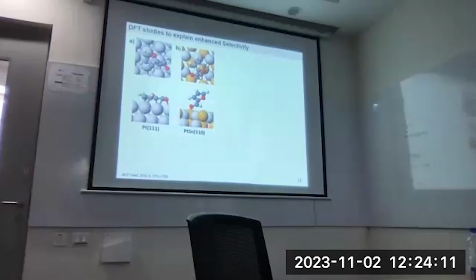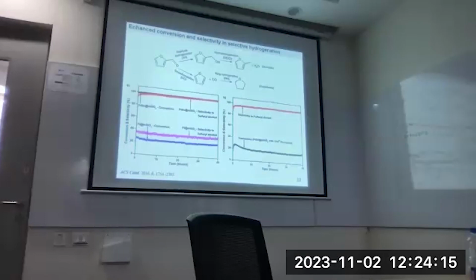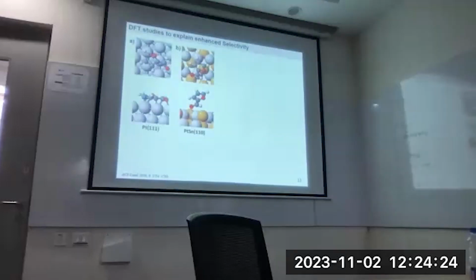Whereas in this case, you're forcing the adsorption only through this bond. And this bond is forcibly adsorbed only on the tin atoms. It's not adsorbing on platinum at all, right? So when you force only this bond to adsorb on the tin atom, the hydrogen can still come and adsorb on the platinum. So the hydrogen dissociates into atomic hydrogen, and then it attacks this bond, and then you form the alcohol.